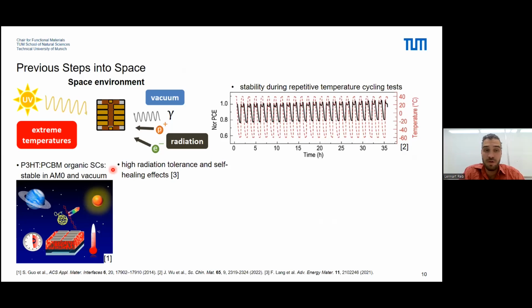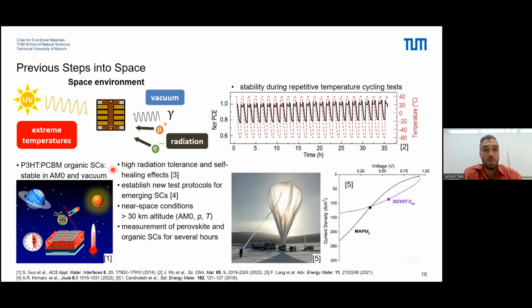And also for perovskites, for example, self-healing effects occur. And this makes them really promising in this regard. However, we need to be careful, because the testing protocols that have been used for decades, developed for the other technologies, cannot be adapted one-to-one for the new technologies, because you might get misleading results, as the tests cannot 100% perfectly resemble the real space conditions. So we need to be careful with our interpretation, and what we need in addition is real-world testing.